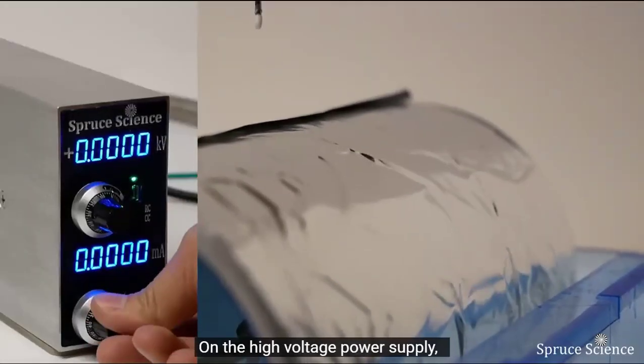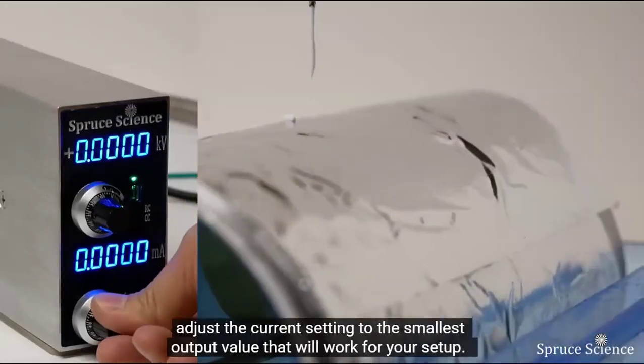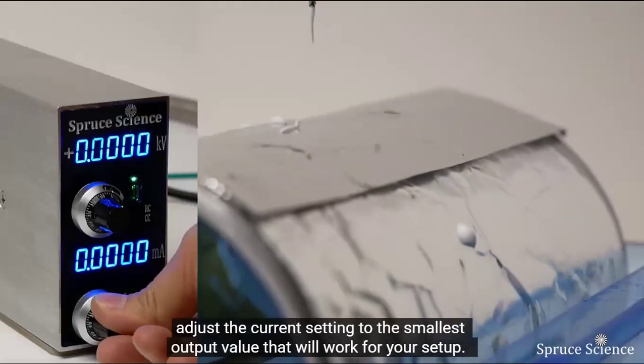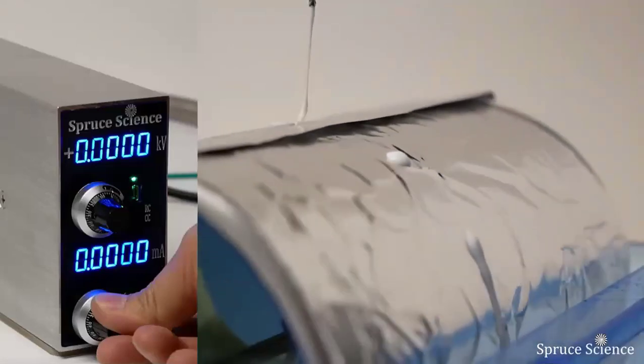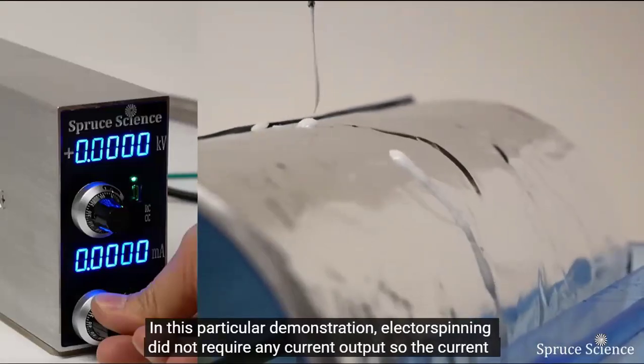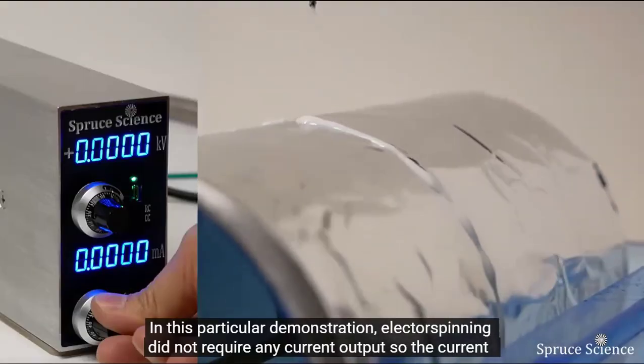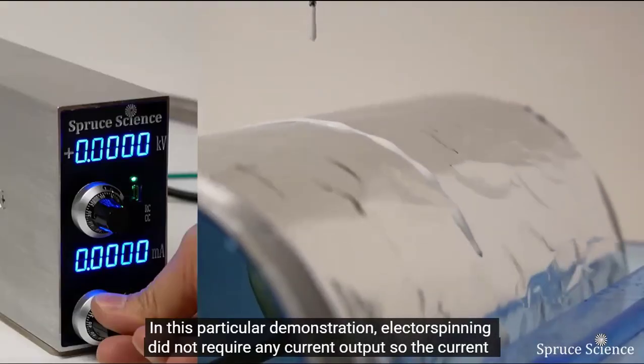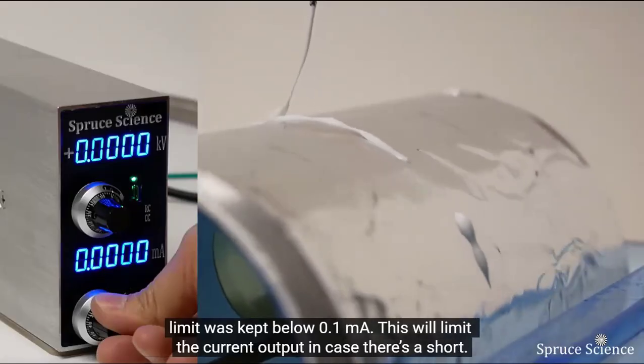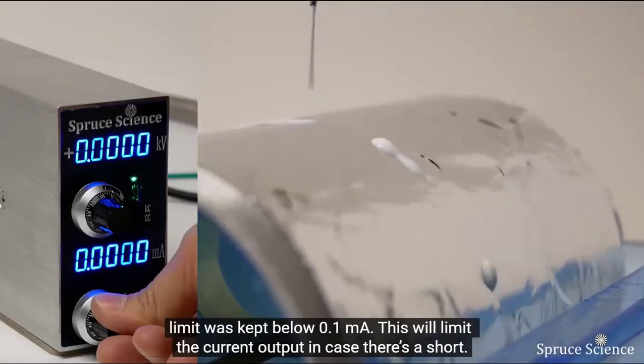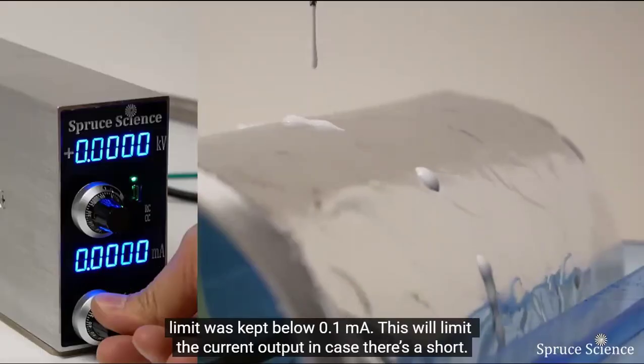On the high voltage power supply, adjust the current setting to the smallest output value that will work for your setup. In this particular demonstration, electrospinning did not require any current output, so the current limit was kept below 0.1 milliamp. This will limit the current output in case there is a short.